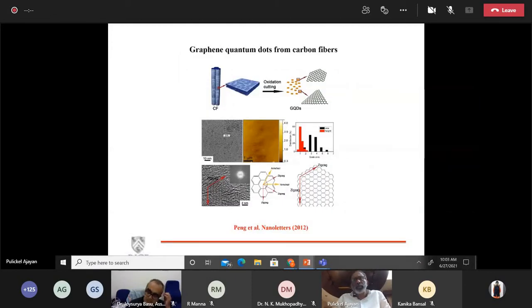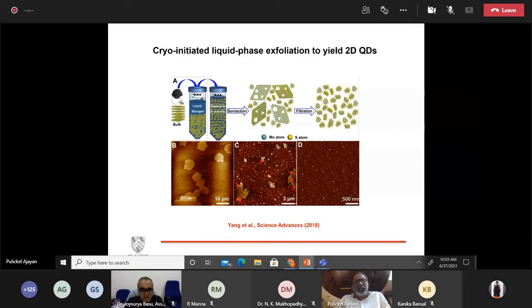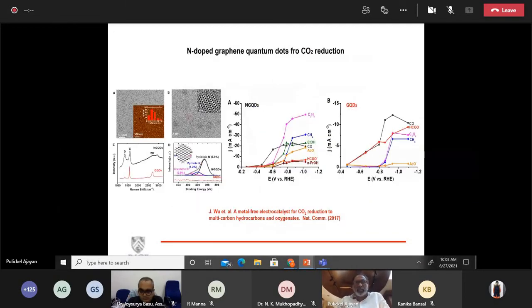And these 2D materials can also be broken down into smaller dimensions, like quantum dots. And we have started to do this for graphene and other types of 2D materials. We recently published some work related to this cryo-initiated liquid phase exfoliation of 2D quantum dots. And again, essentially, we can create quantum dots from pretty much all of these 2D materials. I should say quantum disks rather than quantum dots, because they are 2D. And they seem to have some very promising properties, for example, catalysis. So the nitrogen-doped graphene quantum disks or quantum dots were useful in CO2 reduction as a catalyst.